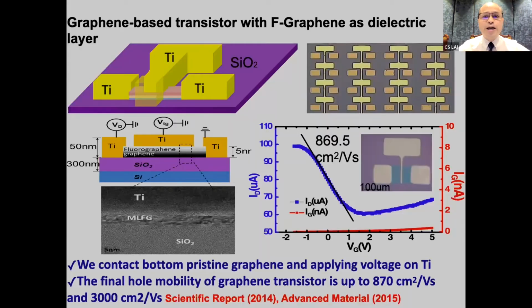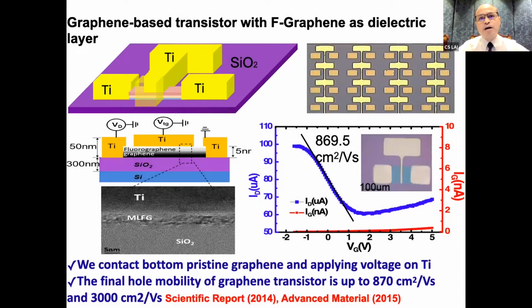So if we have a good facility to prepare the 2D dielectrics and to prepare fluorine doping, and for example, another doping, nitrogen doping, I will introduce you later. We were lucky to fabricate a graphene transistor with a mobility of up to almost 900 centimeters squared per volt second.